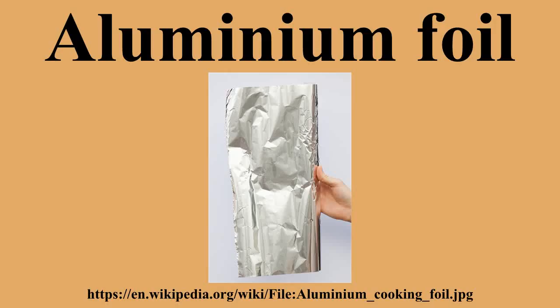Manufacture. Aluminium foil is produced by rolling sheet ingots cast from molten billet aluminium, then re-rolling on sheet and foil rolling mills to the desired thickness, or by continuously casting and cold rolling. To maintain a constant thickness in aluminium foil production, beta radiation is passed through the foil to a sensor on the other side. If the intensity becomes too high, then the rollers adjust, increasing the thickness. If the intensities become too low and the foil has become too thick, the rollers apply more pressure, causing the foil to be made thinner. The continuous casting method is much less energy-intensive and has become the preferred process for thicknesses below 0.025 mm.